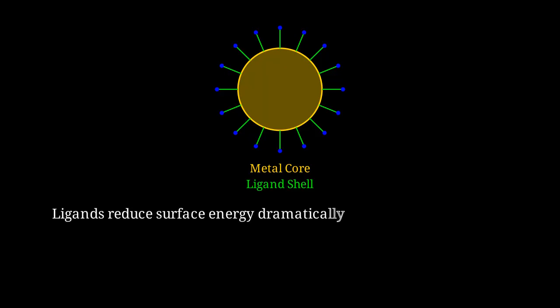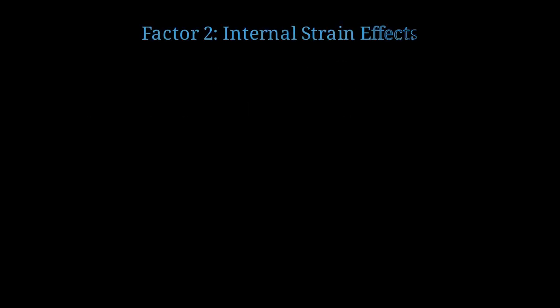Strong ligand binding can reduce the surface energy so much that the effective interfacial energy becomes negative in the Gibbs-Thomson equation. The effective surface energy equals the bare solid-liquid interfacial energy minus the ligand contribution. If the ligand binding is strong enough, gamma effective can become negative. When gamma effective is negative, the correction term in the Gibbs-Thomson equation becomes positive, leading to melting point elevation. For example, gold nanoparticles capped with long-chain alkanethiols can show melting points 50 to 100 Kelvin higher than bare particles of the same size. The second factor is internal strain.